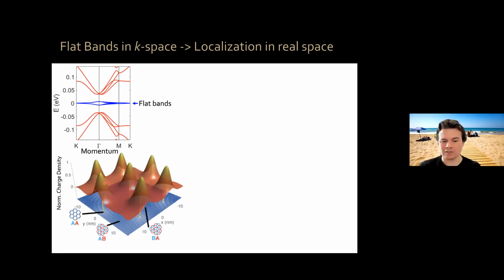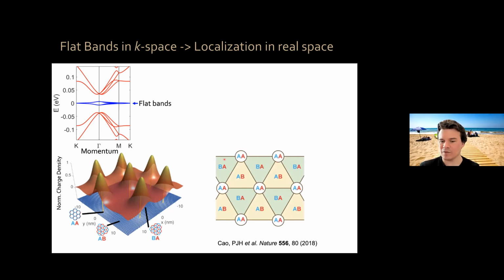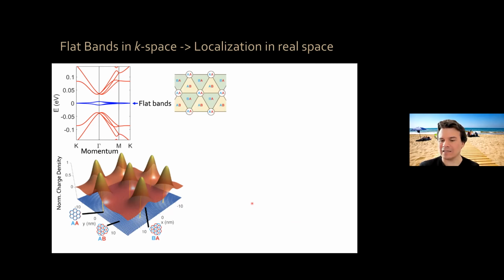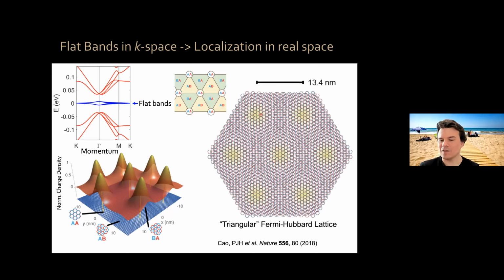These regions are tunnel coupled by regions where, due to the twist angle, the registry of the carbon atoms changes, and locally those regions are of AB and BA type of stacking. So schematically from the top, this is how magic angle graphene looks. You have a moiré pattern with regions of AA stacking where electrons like to sit, and regions with AB and BA domains where electrons do not like to sit. In a slightly more realistic schematic, magic angle graphene has these regions of AA stacking where electrons like to sit. Those regions are spaced by about 13 nanometers.